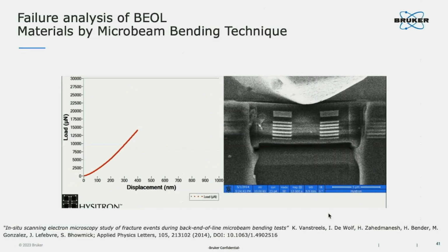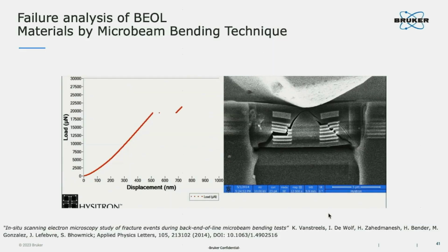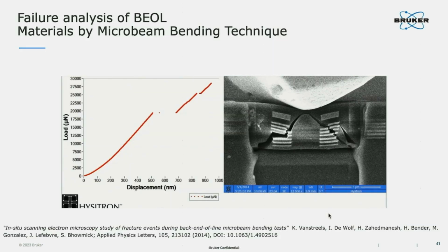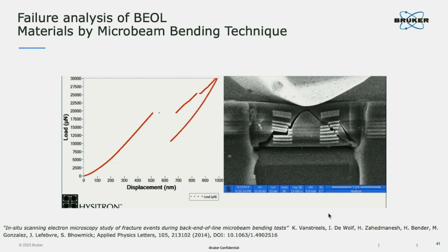This is the beam test here. So we use the focused ion beam to cut the sample. This is the 3D IC. We want to see how strong the 3D IC is. We use Pico indenter with the conical probe to do the bending test. Then with the bending test, we can see how the crack grows by the bending. The mechanical properties can be recorded right here.